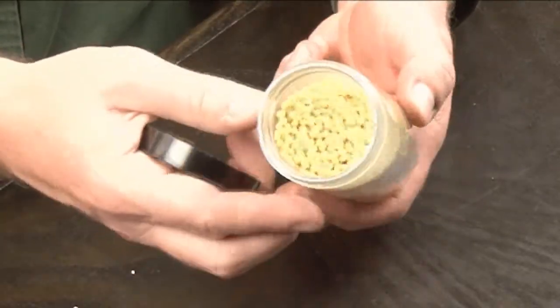And so when the customer came to our manufacturing plant to try and solve their mixing issues, at the time, they would measure the pellet, and they had such a range of the powder consistency, anywhere from 6% all the way up to 20% in these individual pellets, when they would then burn them down and do an ash content. And what they wanted to do was tighten up that spec so that they could have each pellet basically made up of the same consistency of 13% powder.